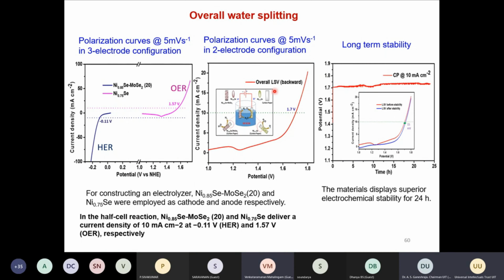This is the combination, the overall LSV backward scan, and it shows that 1.7 volt is needed to split water. Here I have shown the long-term stability of this sample, which is quite stable, with only a slight increase in the potential needed after 24 hours. We also compare before and after stability, and the values do not change much except for a 15 millivolt difference between them. We do this to check the electrochemical stability, how robust the material is.